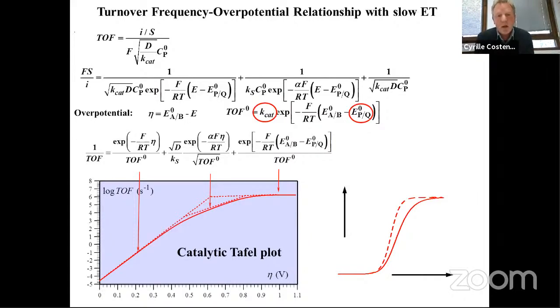So I would recommend in all these cases, if you would like to extract the kinetic information, to try to reach the situation where you observe a plateau, and sometimes, of course, experimentally it's difficult to observe this plateau. But if you reach a CV where the current becomes independent, or if you observe very little dependence on the scan rate, this is a good indication that you probably have reached the plateau, and you can extract the kinetic information on your catalyst.